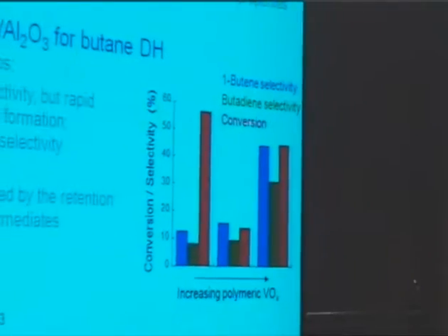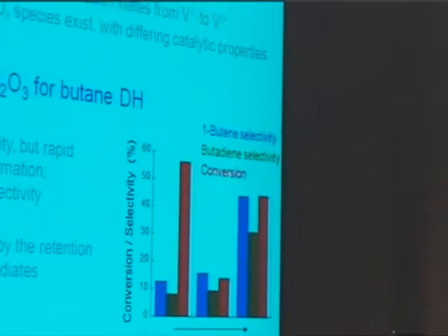However, one of the more interesting results that came out of that was work done by David Jackson at the University of Glasgow. What his group found was that the main cause of deactivation in these reactions, under the conditions that we looked at them, wasn't the formation of large polyaromatic coke ensembles, although you did form these.